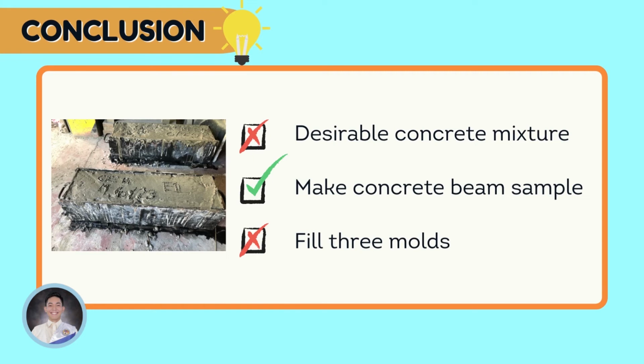Due to certain errors like not being able to take into account the moist fine aggregates and coarse aggregates, the slump was 7 inches, which makes the concrete mixture undesirable. The objective, which was to create a concrete beam sample, was successful. However, only 2 beam molds were filled due to shortage of concrete mixture, and a possible explanation for this error would be having a lesser amount of cement used.